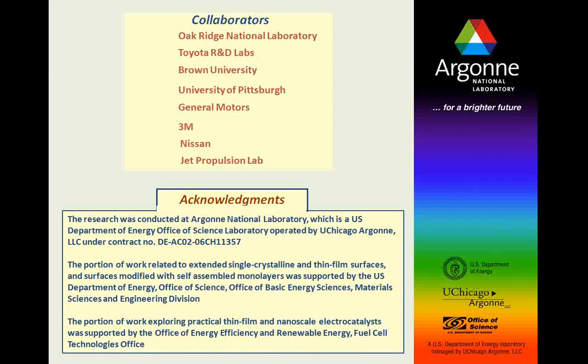We have one question. We'll start off with: you mentioned ways to improve the oxygen reduction reaction, and the question is, one of the causes of catalyst layer degradation is corrosion of the catalyst-supporting carbon during start-stop cycles at high cathode potentials. Are the new platinum-M catalysts more stable to carbon corrosion at potentials greater than 1.1 volts? Do you have any data?